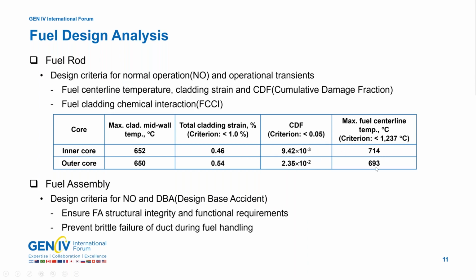And also the maximum fuel central temperature is about 715. It's much lower than the melting temperature. So we confirm the fuel rod integrity is maintained. Also, the fuel assembly design criteria is more than the fuel rod. The integrity of the fuel assembly needs to be maintained in normal operation and also for design-basis accidents. Because to keep the core structure shape, the fuel assembly needs to be intact, even under the design basis event.